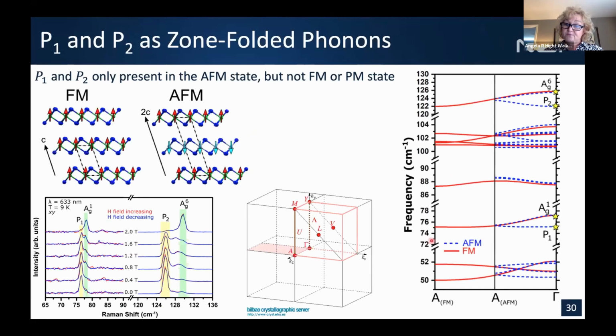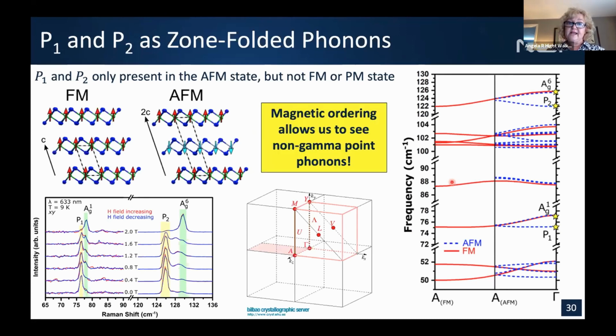So here we have a beautiful theory from one of our colleagues at NIST, where he was able to predict the phonons for the antiferromagnetic and ferromagnetic case. And you can see that as you go from the ferromagnetic to the antiferromagnetic case, those two, P1 and P2, come in quite nicely and agree with what we're observing. So what we're excited about is that magnetic ordering allows us to see non-gamma point phonons. And that is exciting, and the idea that we can use both the phonons and the magnons to track the magnetic properties and lattice properties of these materials.